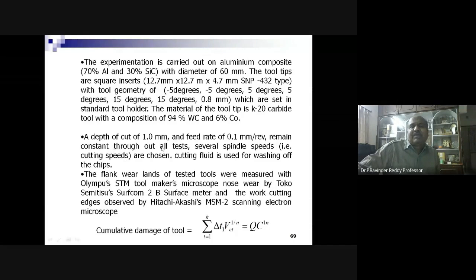The material of the tool tip is K20 carbide with a composition of 94% WC and 6% cobalt. A depth of cut of 1 mm and a feed rate of 0.1 mm per revolution remain constant through all the tests. Several spindle speeds are selected. Cutting fluid is used for washing the chips. The flank wear lands of tested tools were measured with an Olympus STM toolmaker's microscope, the nose wear by a Toko Semitisu's Surfcom 2B, and the worn cutting edges were obtained by a Hitachi Akashi MSM2 scanning electron microscope.